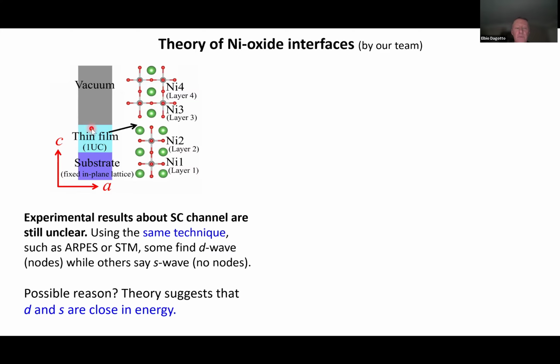We consider a thin film with 1 unit cell. For the benefit of the audience, let me also give you a little warning about the language used. Turns out that the atomic arrangement of the nickelates has this extremely annoying feature: you have a bilayer here, one plane, the other plane, and then the other two on top are shifted by half a lattice spacing. Consequently, the true unit cell involves 4 nickel-oxygen planes, as opposed to only 2. But they are very weakly coupled anyway. But to be very strict, 1 unit cell involves 4 of these. It's different from 1 single bilayer.